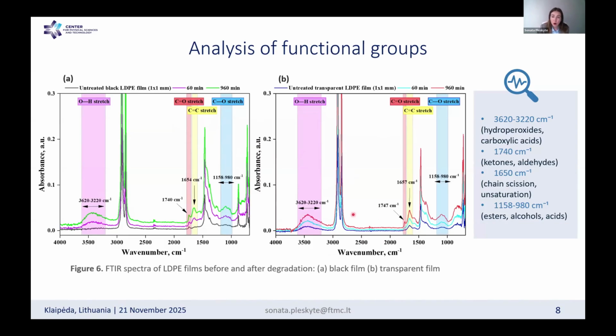Also, you can see the formation of the carbonyl group over here. You can see the increased peak, which corresponds to the carbon double bond carbon stretching, but I want to draw your attention that these changes are less pronounced than in black colored LDPE films. And in general, to summarize this slide, I could say that the spectral changes that we found after the photocatalytic degradation, such as new peak formation and the branching of already existing peaks, indicate chain scission, also branching, as well as formation of new methyl and methylene groups, and also a decrease in the crystallinity within the polymer chain.